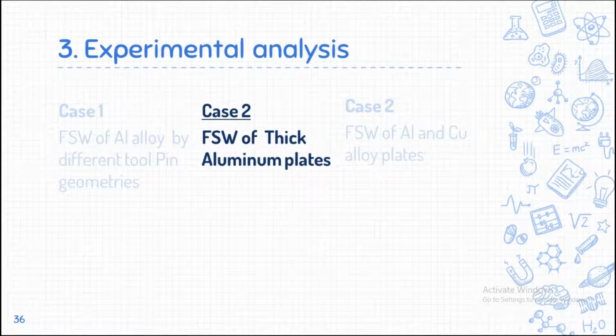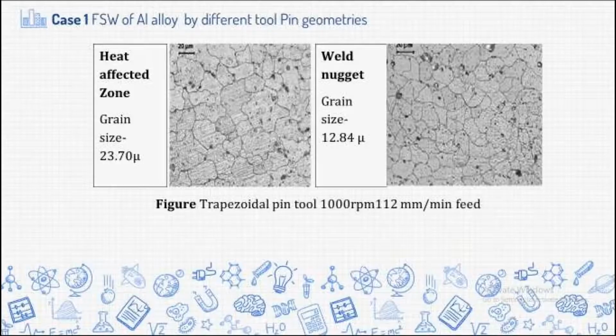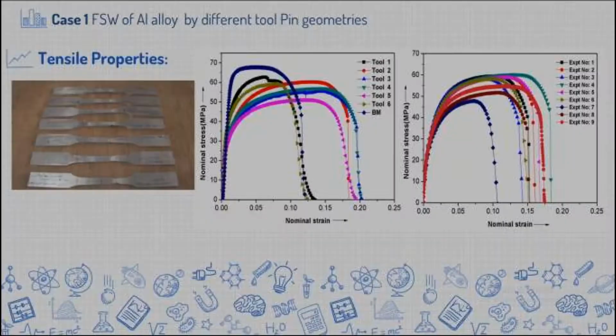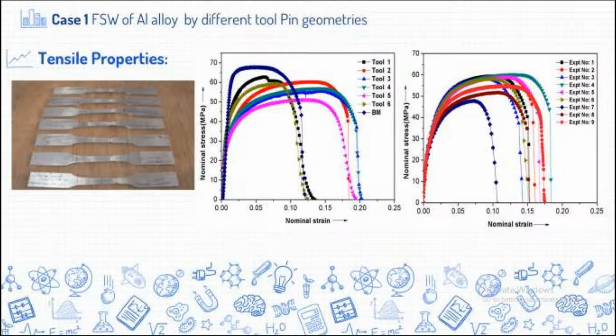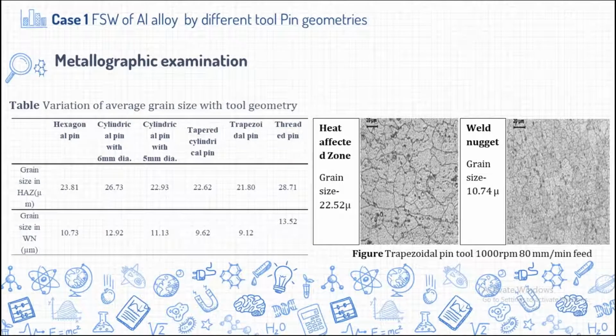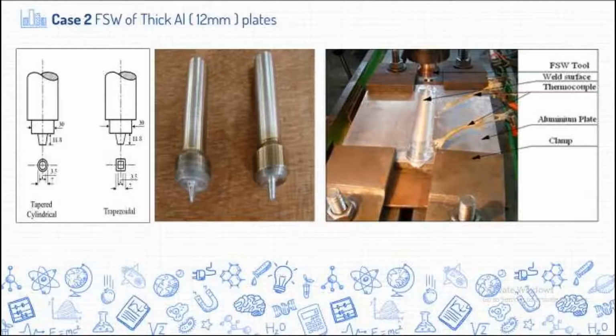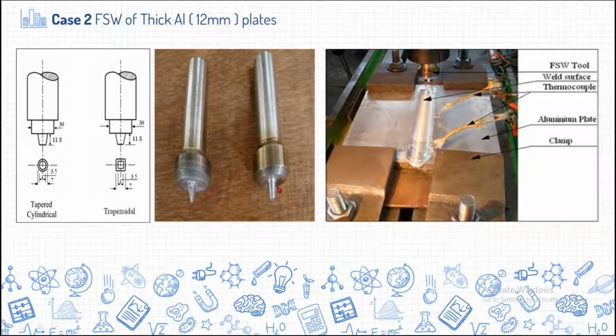And the second case, friction stir welding of thick aluminum plates. So these tools, whatever we considered in the previous studies, from this we observed that tapered pin tools and trapezoidal pin tools are performing well for 6 millimeter welding of aluminum. But we wanted to see whether these tools are suitable for high thickness plates also. So we have taken around 12 millimeter thick aluminum plates. We tested the same tools, like tapered cylindrical, some tapered pin, and trapezoidal pin. We fabricated some tools and tested them for high thickness welding.